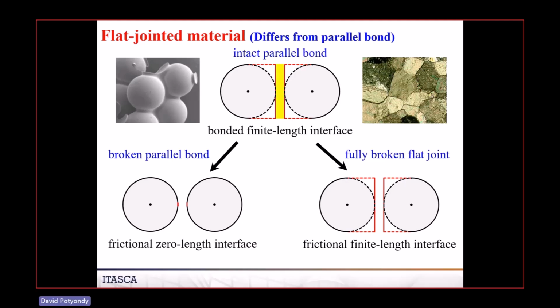And when the thing fails in UCS, it all just fails by micro tensile failure because you set the micro shear strength infinite. What's happening is that it starts to crack with these little tensile breakages all throughout the material. It cracks in one spot, then it cracks further away, then somewhere else. You get this heterogeneous distribution of micro cracks, which is what happens in real rock as well. But then it localizes at one spot and you get this zoom, zoom, zoom, and this axial split forms. That's all just driven by micro tensile failure. So there's nothing you can do anymore with that model to raise its UCS.